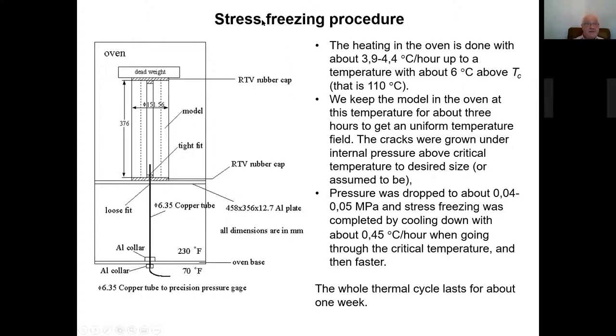Now, what is the scheme of stress freezing, the procedure itself? So, the photoelastic model sits here. You have a pipe with air pressure into it. You, of course, make the hole and initiate an artificial crack. Then you glue some rubber caps, top and bottom, and you start to increase the temperature inside the oven. And this has to be done very slowly. So the heating of the oven was done at a rate to go a little bit above the so-called critical temperature.